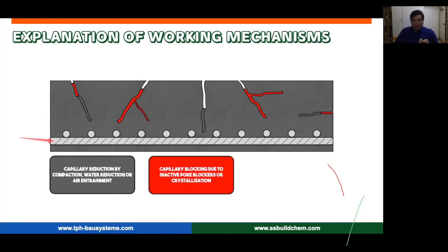Then the second part is achieving capillary blocking due to inactive pore blockers or crystallization. In this case, there can be something like finely divided materials. In some cases, crystallization refers to byproducts of hydration, that is lime that gets deposited into your capillaries and blocks them. In other cases, crystallization also refers to the secondary hydration of some type of pozzolanic activity, which densifies the system as a whole. So capillary blocking is another mechanism by which it can work.